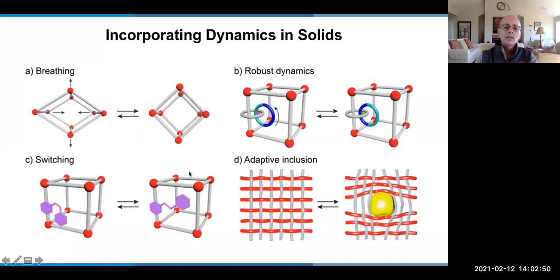So I would say carrying out dynamics in this way, like a breathing solid, is not a very healthy way to do it, because as the solid expands and contracts, bonds break, and if some bonds don't reform, then the material will break. So this is not a good way to do dynamics, because ultimately the material breaks. However, it's a lot better to interlock things physically, like we propose here, that is, leave the backbone intact and not dynamic, and add dynamic units onto the backbone, as shown in these two cases.